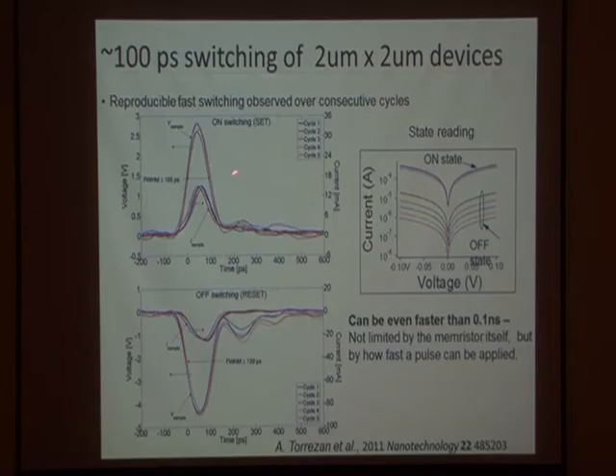Once he does that, and he did that 5 times, he pulsed it with a pulse generator that provided us with 100 picosecond width. And in that amount of time, he was able to switch it both on and off. So this was pretty cool. More recently, they were able to get 85 picoseconds because we got another pulse generator. And if you want to go faster than that, there's an exponential price on the pulse generators as you go below 100 picoseconds, so we can't afford it. But the point is this: these devices switch much faster than most of the applications.